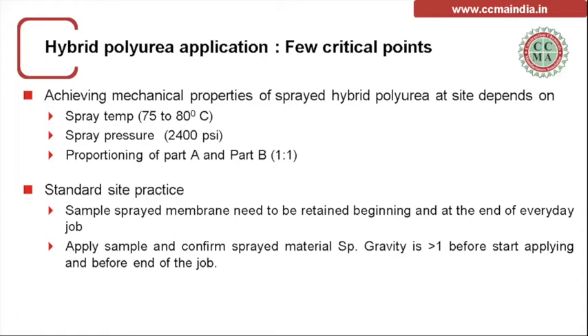As I told you in the beginning itself, for any waterproofing, workmanship is very, very important. Awareness is important. So what is the standard practice at the site to achieve this? Sampling. We have to spray the membrane every day before starting the job and every day at the end of the job. This needs to be recorded and kept for testing the properties at any time. And one most important thumb rule is that the material specific gravity should be more than 1 when we spray this, because the mixed density will be in the range of 1.03, 1.04. If there is any lacuna in temperature or pressure, and the specific gravity goes less than 1 because of air pockets in the membrane, then the intended mechanical properties will not be achieved.